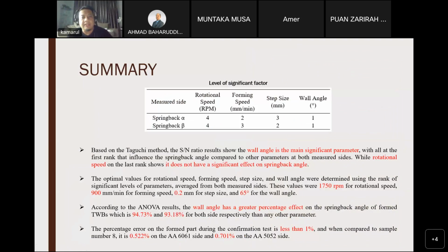Okay, as a summary, based on the Taguchi method, the SN ratio results show the wall angle is a significant parameter that influences the spring back compared to other parameters on both material sides, while rotational speed ranks last and doesn't have a significant effect on the spring back angle. The ranking of the SN ratio shows the ranking of the significant parameters. For spring back on 6061, the wall angle is very significant. The second is forming speed, third is step size, and the last is rotational speed.